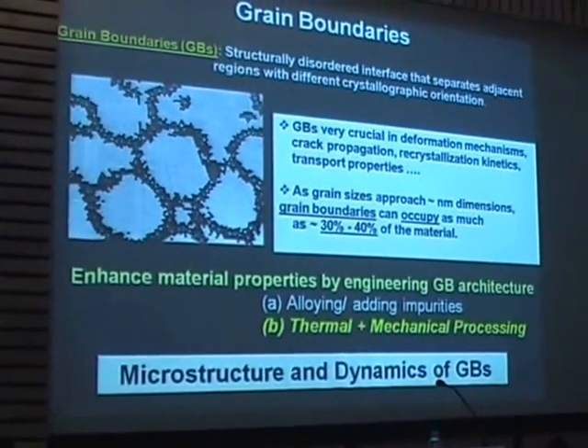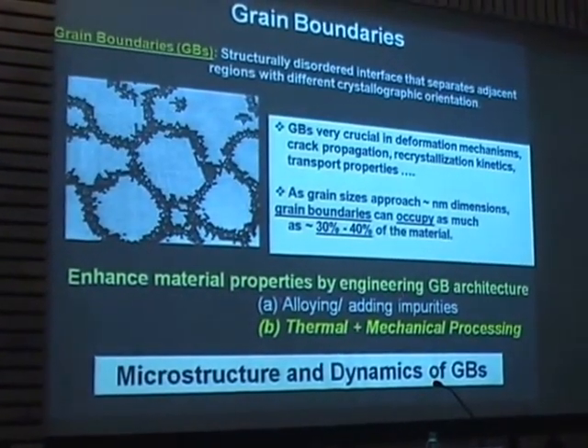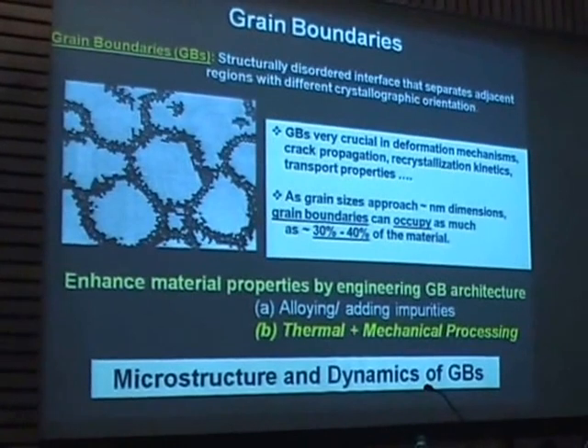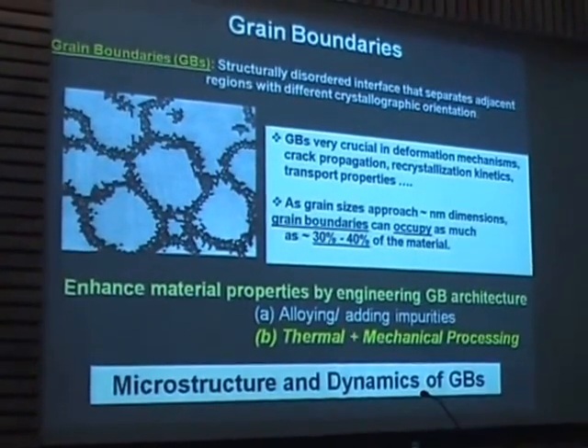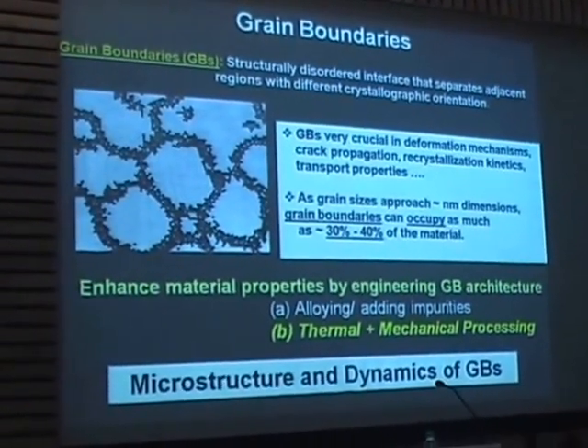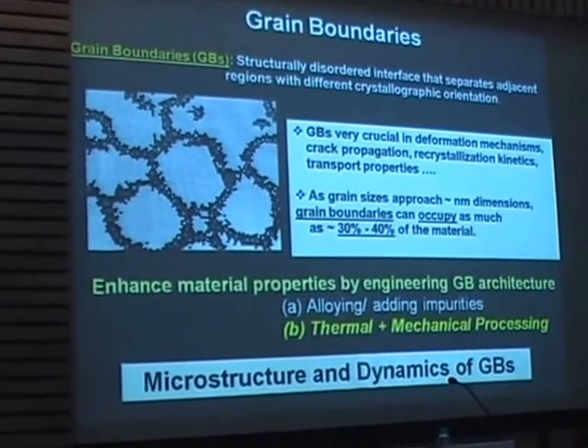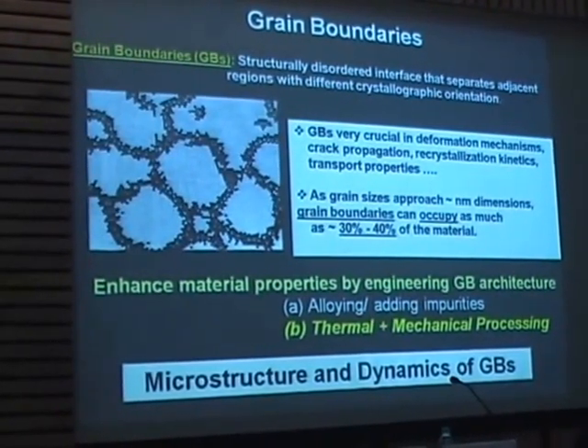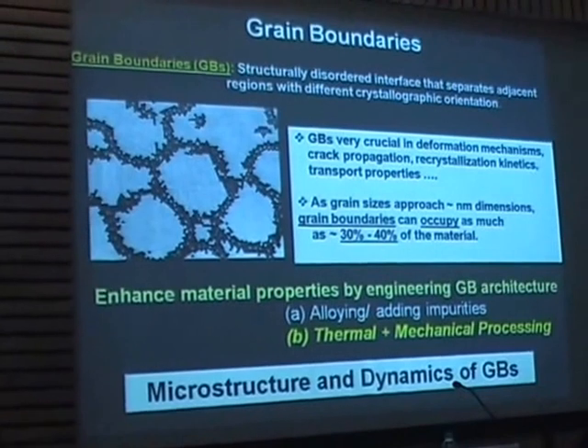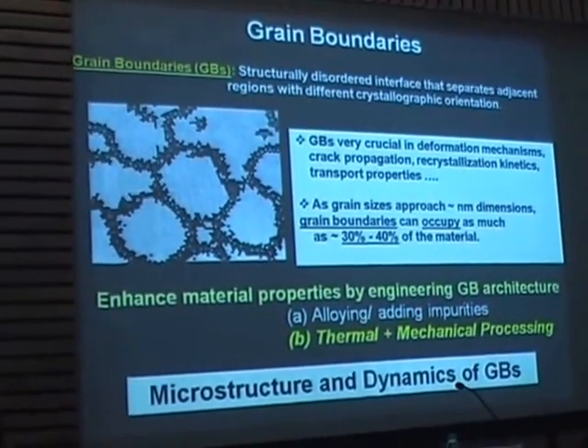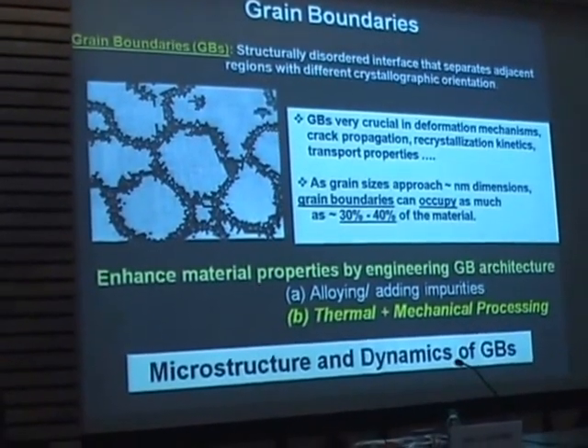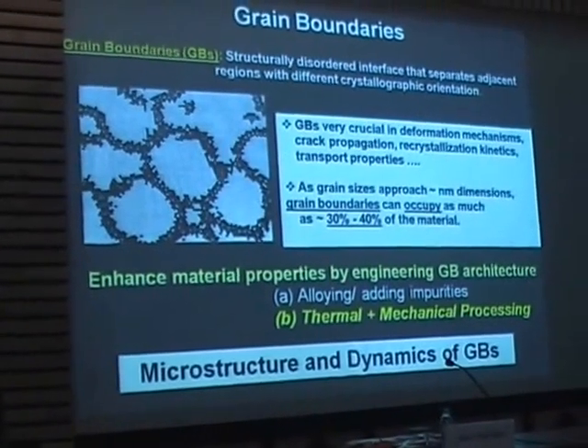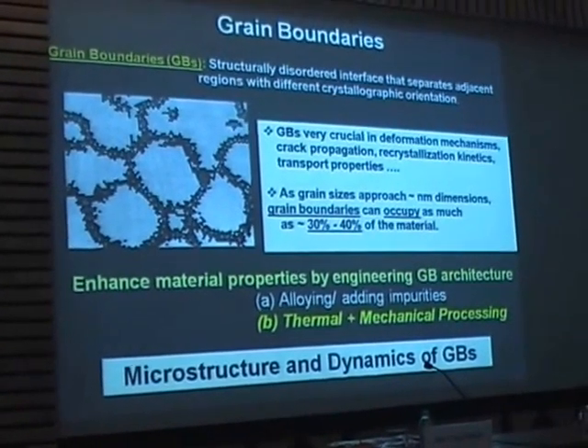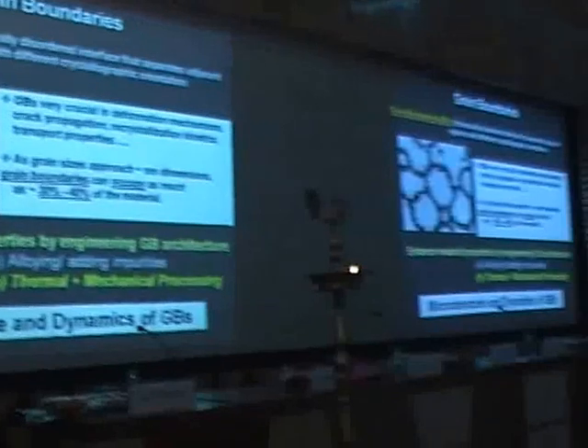And the idea is to enhance the material property. And this material property is done by alloying. For example, gold. When you take 24 karat gold or 22 karat gold or 18 karat gold, essentially you are alloying with something and you are changing the property of gold. The second one is you do the mechanical treatment and make the grains grow at the expense of some other grain. So this is the grain boundary engineering, which is very critical for application.